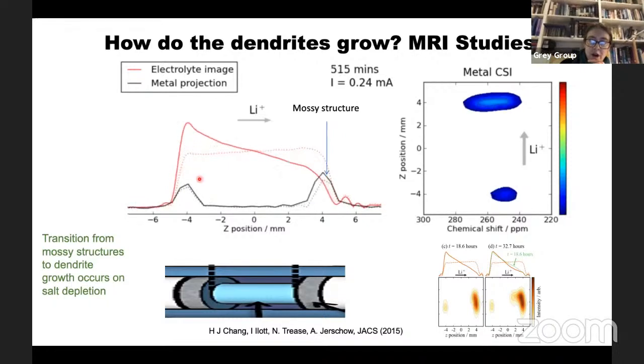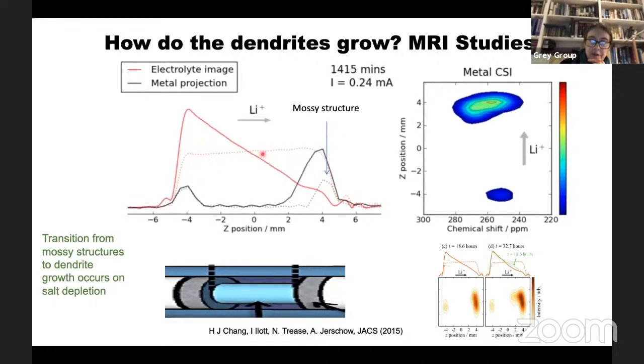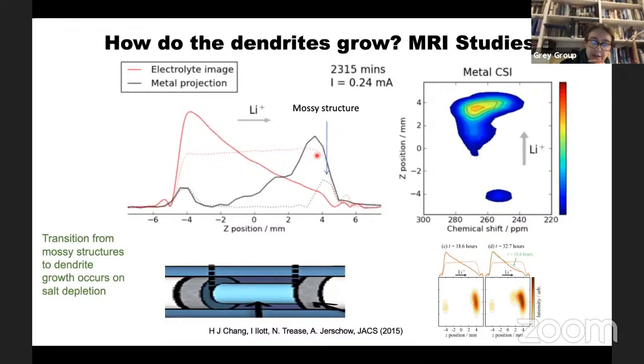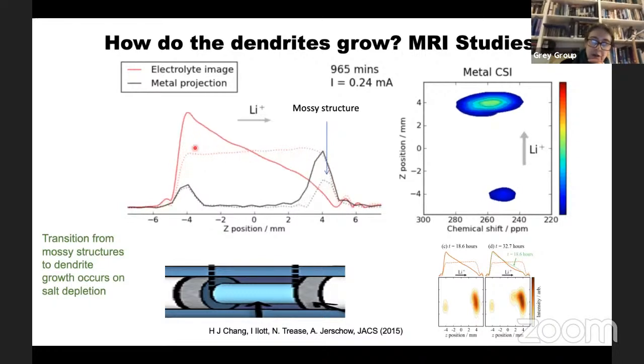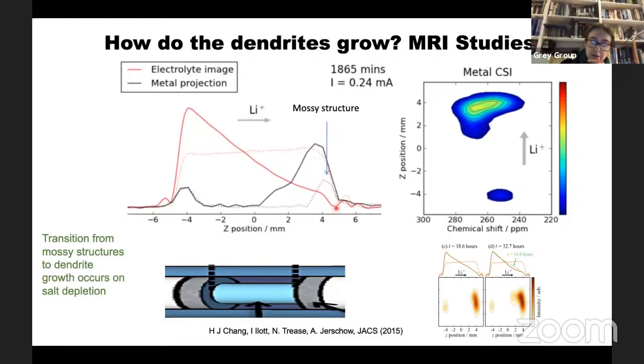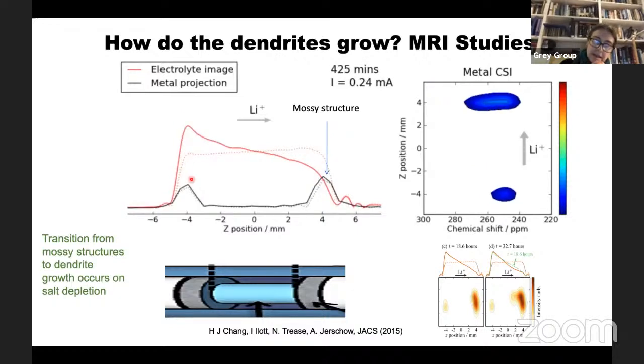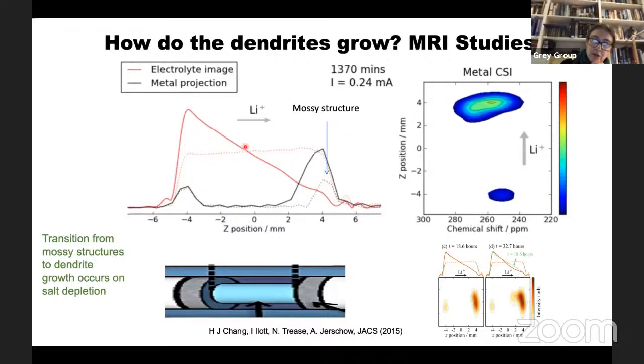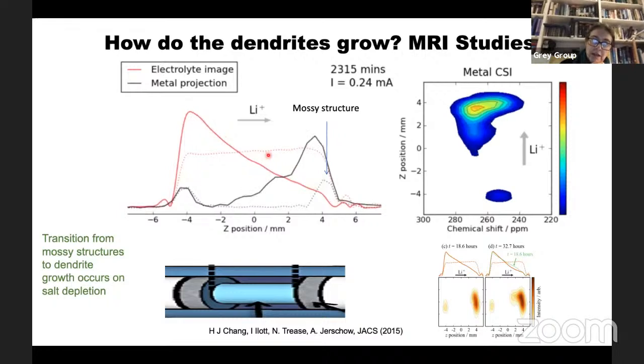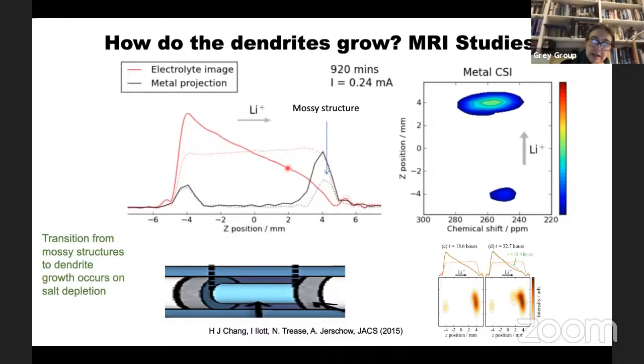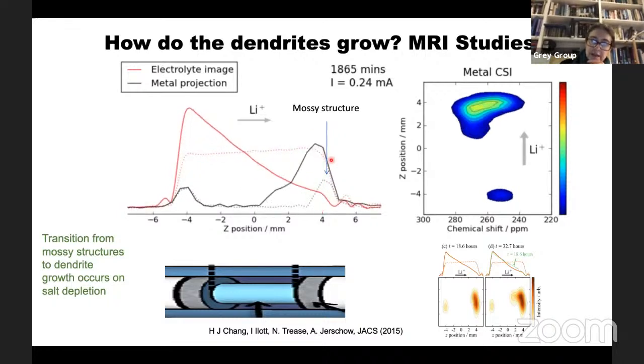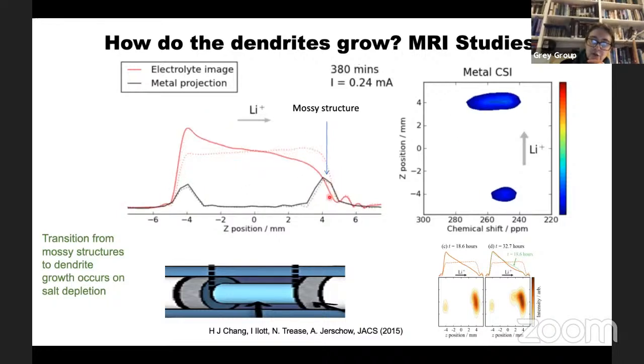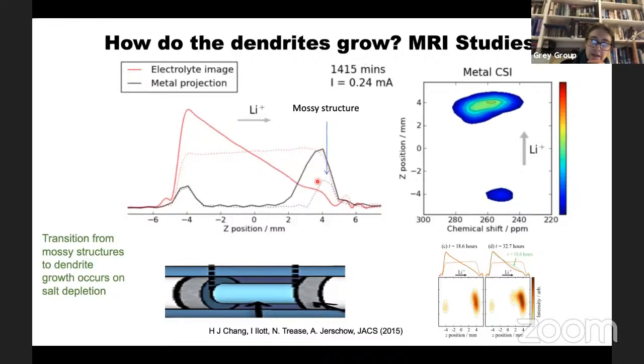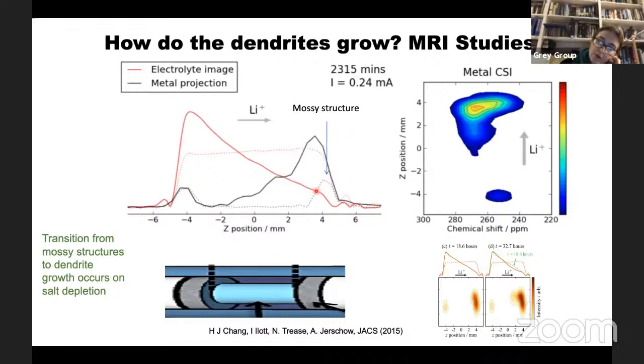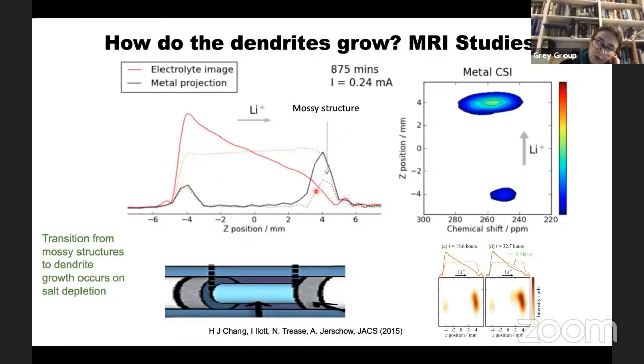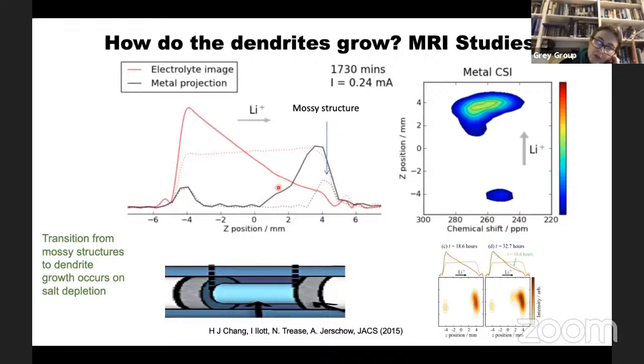And this distance here is the distance between two lithium sheets. As I flow current, the lithium ions move in this direction. The PF6 minus counter anions move in this direction. The lithium ions deposit, but because the PF6 minus anions can't, you build up this concentration gradient. So that's what you're seeing in red, is the beginning, and then this is the end. Now watch the lithium. As the lithium starts to grow, first of all, it grows near the surface. And then when the electrolyte concentration drops to 0, the dendrite starts to grow.